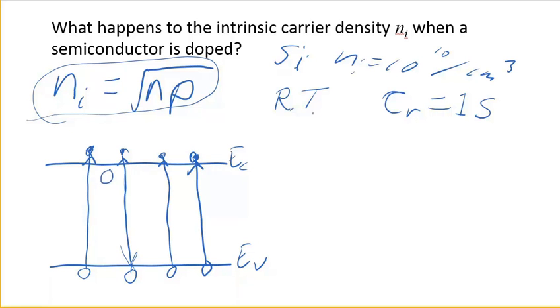Now you add dopants. Let's bring in four donor dopants. So they each kick in an electron. And so now we have eight electrons in the conduction band. All eight electrons still have to follow this rule, that they get to stick around for one second. Except that if there aren't any holes left, then they stick around longer. But as long as there are holes left, they stick around for one second.